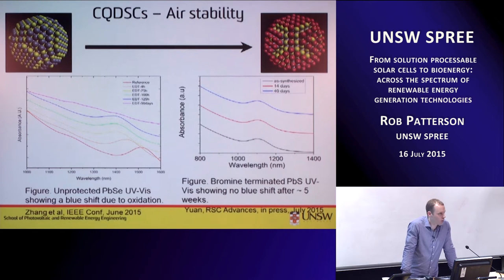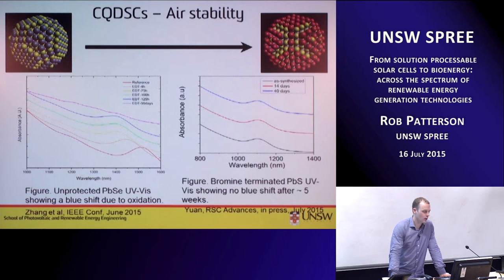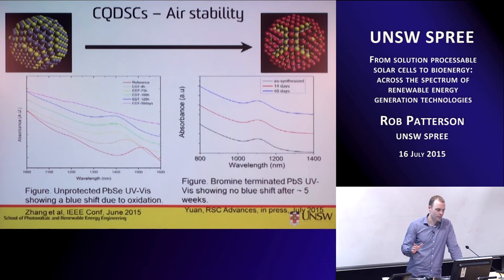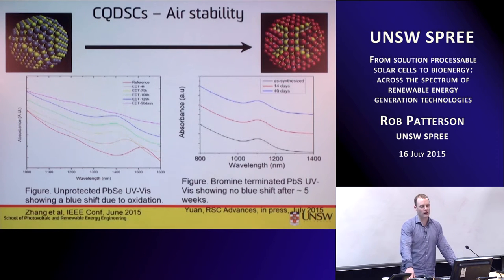Okay, so here's something a little bit more interesting. As we know, in general, solution processed materials have problems with air stability, and quantum dot solar cells are no exception. What has recently been discovered is that if we cap these materials with halide atoms, then we can slow or stop the oxidation of the material. So if we take a quantum dot that looks like this and we cap it with something, in this case you can think of it as bromine or iodine, then we can prevent shifts in the UV-Vis spectrum, which are due to oxidation. Here we have bromine capped lead sulfide, and after about 5 weeks you can see that there's basically no shift at all. That's because of the bromine capping. So this is one way that in this material type we are able to stabilize the quantum dots against oxidation and make them last, so our cells last a little bit longer.